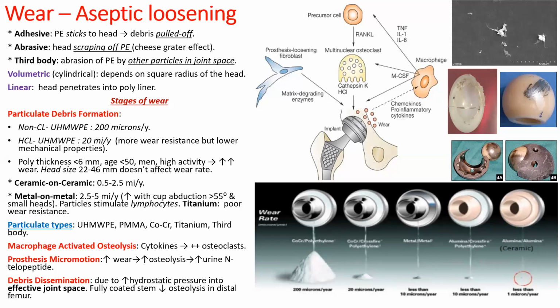Wear passes in four stages. There will be formation of debris particles. The size of these debris particles differs according to the bearing surface. The least debris particles are with ceramic on ceramic, and the biggest is with non-cross-linked ultra-high molecular weight polyethylene. The type of the particles depends on the bearing surface, as I said.